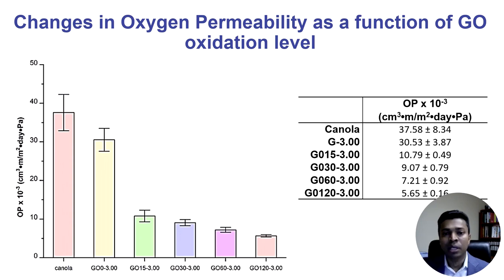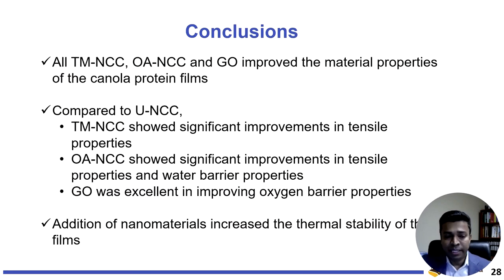So right now we are looking at improving the material properties using a combination of nanocellulose and graphite oxide in the same material, so we can improve the material strength while at the same time improving the oxygen barrier properties as well, not just the water vapor permeability. With that, we realized that by using nanomaterials and chemically modifying them in different ways, we can actually improve biopolymer-based materials into value-added applications.